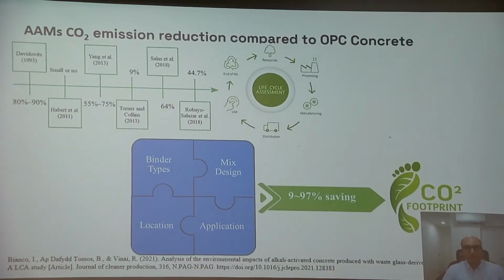Alkali activated materials, on the other hand, have proven to be effective in lowering the CO2 emission compared to cement. But the amount of reduction is different in different reports by different researchers. So as we see throughout the years, we have versatile values for that. But in general, depending on the binder type that is selected, the mix design, the location of the project, and the application of the alkali activated binder, it could be between 9 to 97% of saving in carbon reduction.